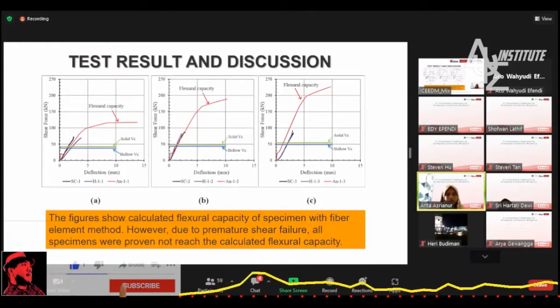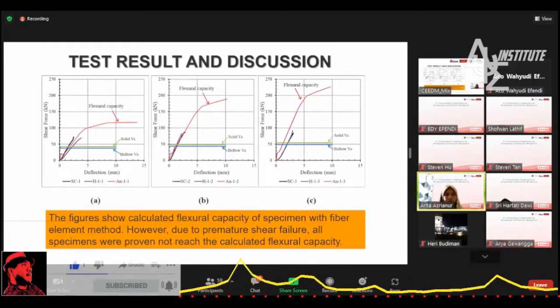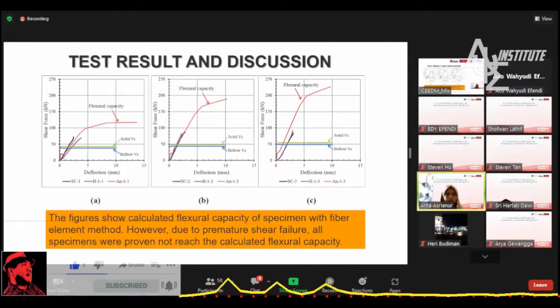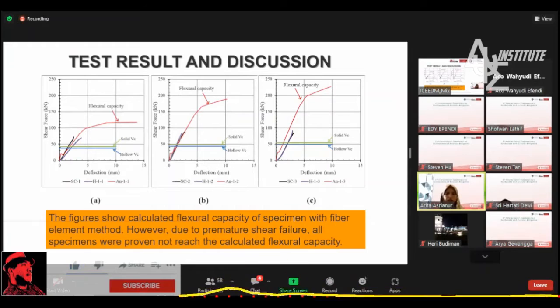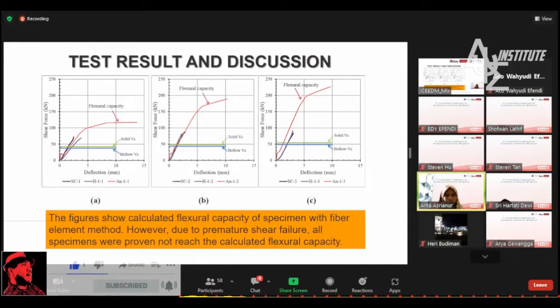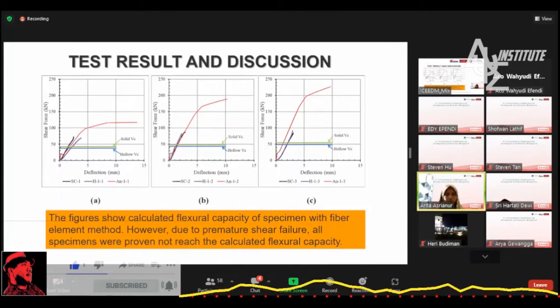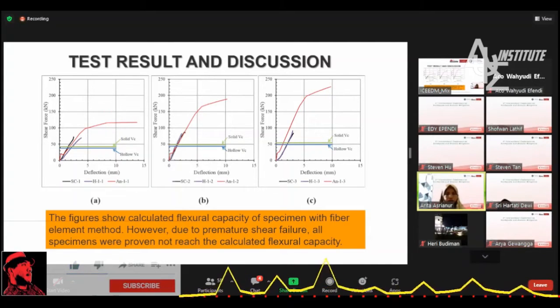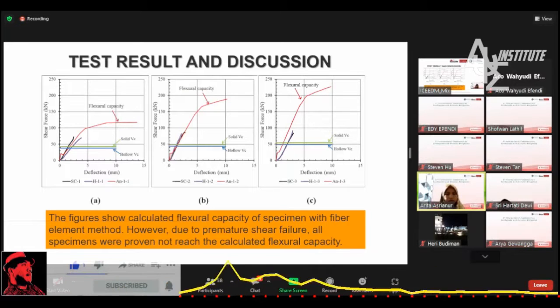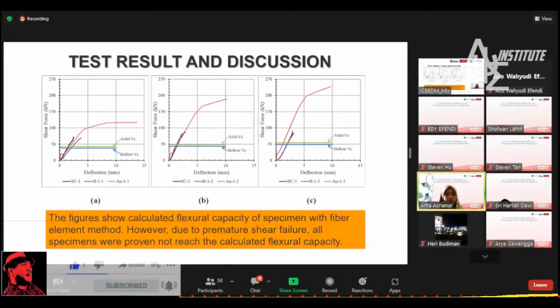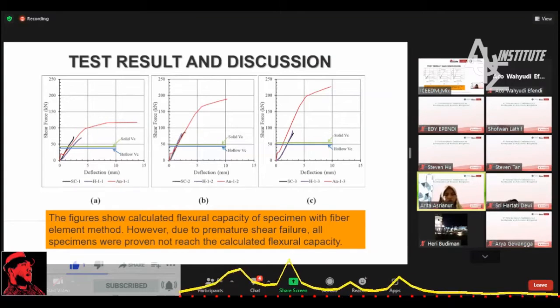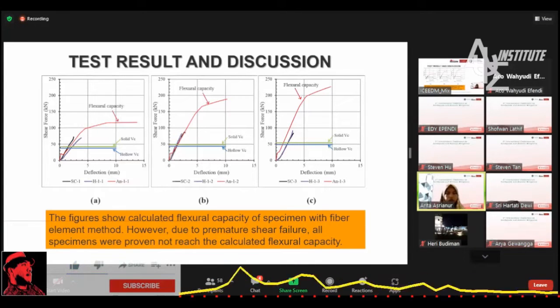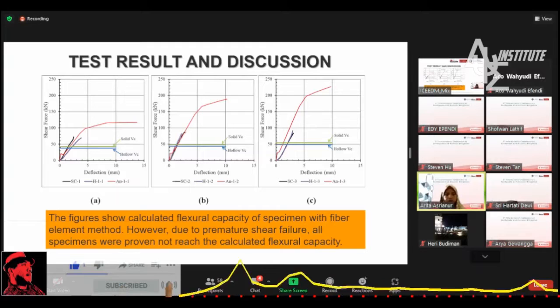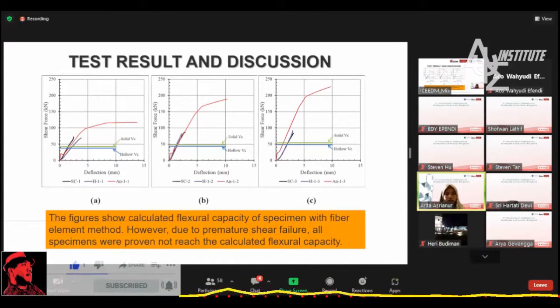And this picture shows the comparison of shear force versus deflection curves between solid and hollow specimens. This picture also shows the calculated flexural capacity of the specimen with the fiber element method. However, due to premature shear failure, all of the specimens were proven not to reach the calculated flexural capacity.